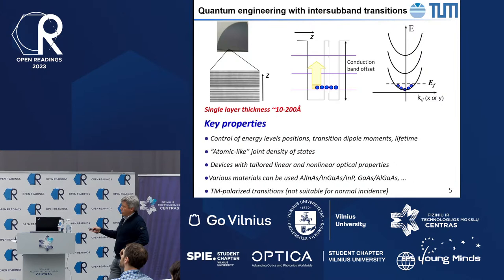Of course, electrons are fermions, and you cannot occupy the same state with more than two electrons, but luckily, electrons are free to move in the plane of the semiconductor. So for this ground state that corresponds to electron quantization in the z direction, you actually have many states of electrons that have different in-plane momenta, k parallel. And so you can put a lot of electrons into that state, and they will all have different in-plane momenta. But since the optical transitions are all vertical in k-space, the momentum of electrons is going to be preserved as the electron transitions from this state to that state.